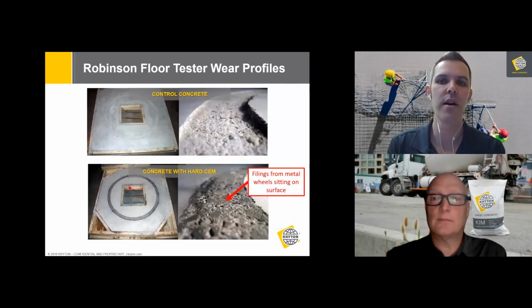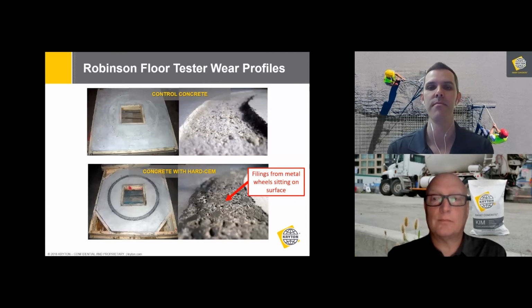So when this test is run, that machine we were just looking at, it rotates. Typically, we run it for 5,000 cycles. You can modify that test and run it for longer if you'd like. And when the test is done, you can directly measure the depth of wear that's been cut into the concrete by these hardened steel wheels using a pair of depth calipers and measure the abrasion resistance of the concrete directly.